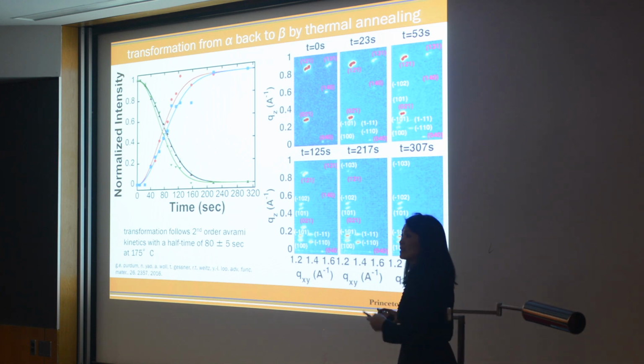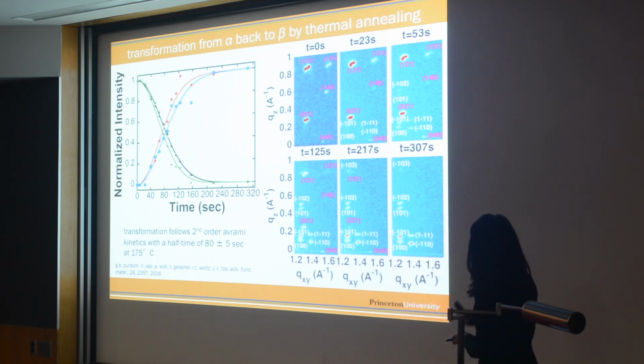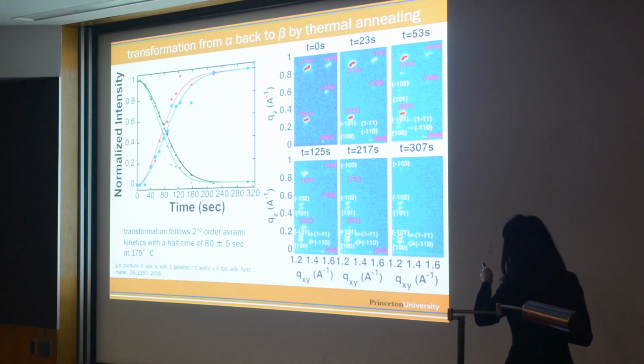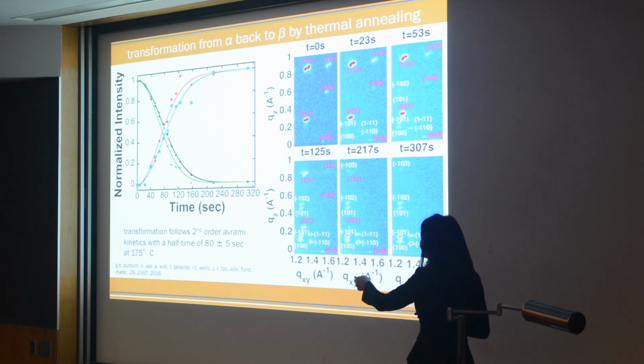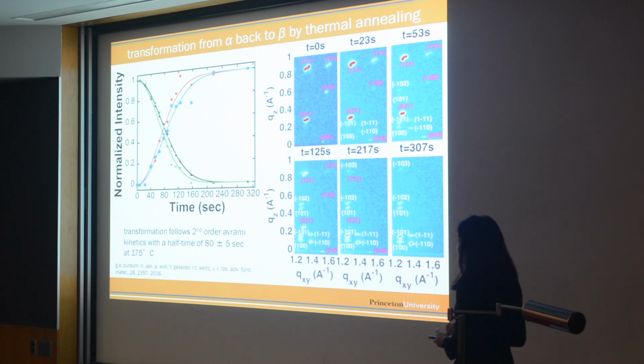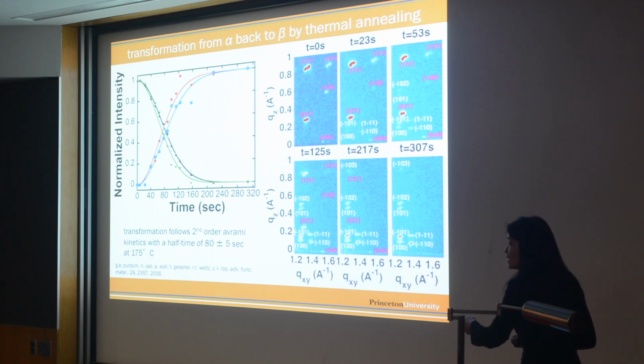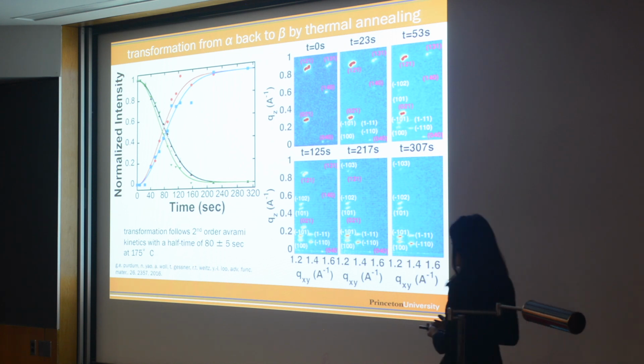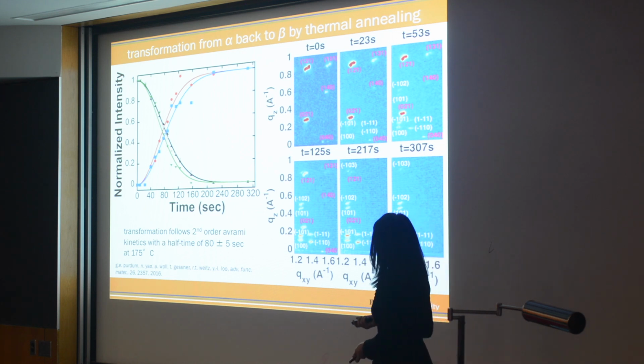This is data capturing the transformation from alpha back to beta. This time we're using X-ray diffraction, and we're thermally annealing the film. You can see that the reflections identified in red are slowly decreasing in intensity, and the white reflections are growing in intensity as a function of time during isothermal annealing. And this is shown here. This is the alpha phase data, and this is the beta phase that grows with time. Again, we can fit this data to the Avrami equation, and we can again get a half time. And again, it's second order, telling us it's a nucleation and growth process.